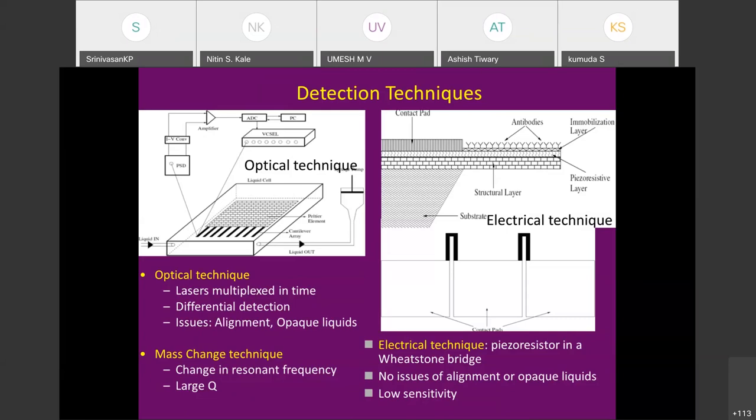Please try to understand that from the E-k diagrams, which a lot of physicists have studied, and we will not go deeper into that, because of the application of stress there is a change in the effective mass of the charge carrier. If the effective mass changes, the mobility and the carrier concentration both will change. From the band diagrams, this can be verified. And if both change, then the conductivity or the resistivity both will change, and if resistivity changes, there will be a change in resistance. The change in resistivity because of stress can be pretty large. You can have your gauge factor in tens and even hundreds. Some people talk about carbon nanotubes, where the gauge factors are of the order of even 1,000. So I'll leave this topic, but this was a digression.